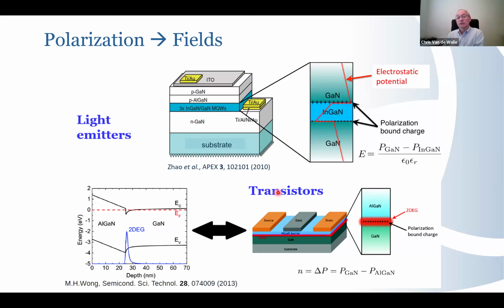In transistors, in electronic devices, it's a bit of the opposite. There, the polarization fields are actually beneficial and functional because you now have a thin layer of, for instance, aluminum gallium nitride on top of gallium nitride, and you again have a polarization field, and that polarization field actually helps you confine electrons at the interface between AlGaN and GaN, and that gives you the sheet density of electrons that you control in a transistor to get all the functionality. So again, knowing the polarization on the gallium nitride side and the aluminum gallium nitride side lets you determine the polarization discontinuity, and to some approximation that then gives you a density of two-dimensional electron gas.